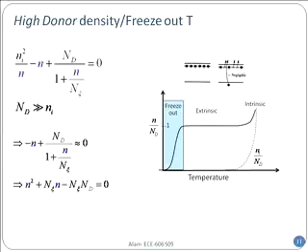And we'll check that. Once you have done that, drop the first term, Ni squared divided by N on the top equation. Then you will get something simple, and you can see that will lead to a quadratic equation for N. N squared plus N sub xi multiplied by N, and the whole thing.